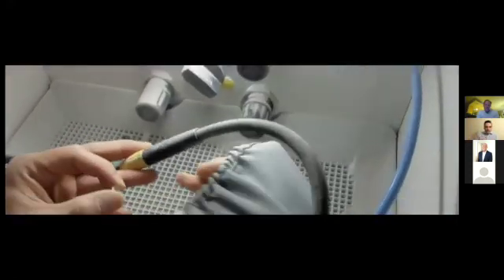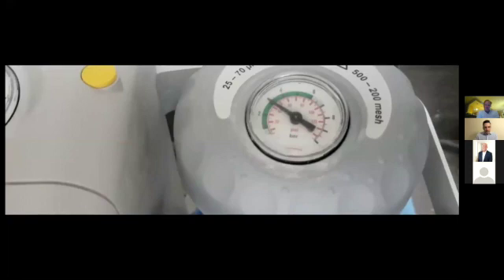So basically from these studies, we found two things. I'll stop this video while I talk. So we found two things. One is that you need to sandblast zirconia, and two, that you need to apply MDP, and that allows you to get a higher bond in bond strength studies.